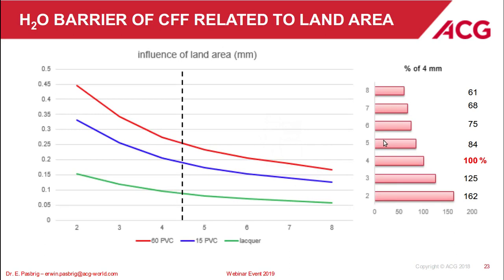This is the barrier related to the width of the land area, so from the cut side into the distance to the cavity. Standard-wise, 4 millimeter is used in your industry. If you are going less, so reducing the land area, you are saving material, but the time until the gases and humidity will migrate into the cavity is reducing, so you get faster the increase of humidity and oxygen in the cavity. If you are increasing the land area, then definitely the barrier for your product, the shelf life, is increasing. I guess it would be difficult to convince your marketing to have a blister with 8 millimeter land area because it becomes bigger. And this is more costly, and if you compare it with the material your competitors may have on the market, the blister would be bigger.